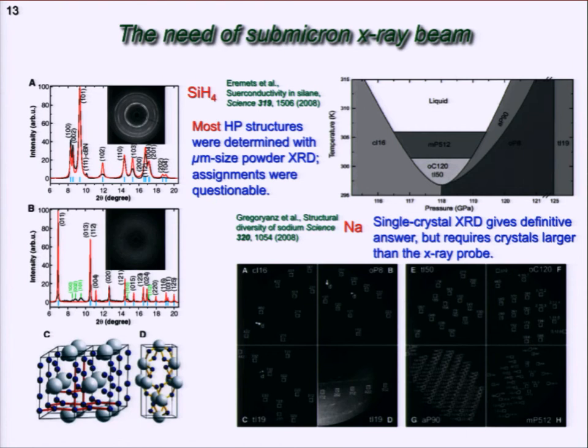But if you increase the pressure enough, hydrogen will become a metal, and that has been shown at very high temperature, near the plasma state. But if you can make hydrogen a metal at ambient condition, it has many really weird structures and properties. For instance, one prediction is that it becomes a room temperature superconductor. Another prediction is that it becomes a very good fluid, much better than lithium. Lithium battery is one of the major applications, but not everyone is pushing any application. But if you can get some proton conductivity from hydrogen, that would be really great. Also, it's related to the fusion field and many other things.